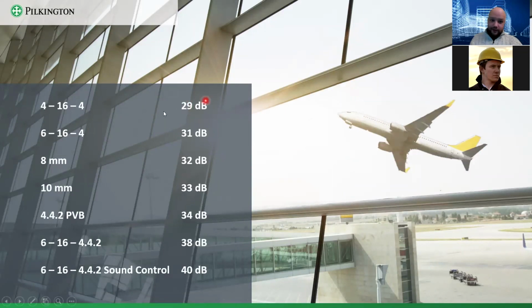So if we get Rw on a very standard IGunit, it will be around 29 decibel. Different types of glass, different thickness of glass, a little bit more. Remember, 1 decibel difference is nothing. 10 decibel difference is doubling. Single sheet of 8 millimeter, heavier, more solid, again an increase. Thicker the glass, even more. Laminated glass, even more. And then we have an IGunit with the laminated glass and acoustic laminated glass.